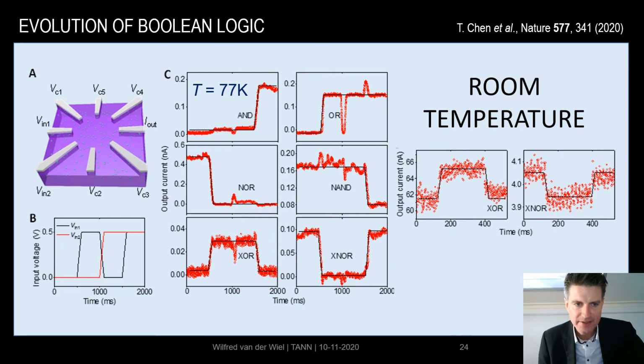But the nice thing is that if we push our device a little bit to the limits, we can even see the exclusive OR and exclusive NOR gates at room temperature. Although you see that the signal to noise ratio is not so high as at lower temperature here. In principle, we think this can be ascribed to non-idealities of our present device structure. So we are quite hopeful that we can operate our devices in the next generations at or very close to room temperature.